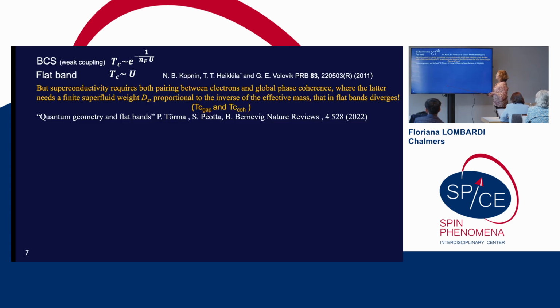However, flat bands have gotten so much attention because essentially if you have BCS, the TC is exponentially dependent on the product between density of states and interaction. Instead, in a flat band system, you can get that the TC becomes linear with interaction. So you could boost, in principle, superconductivity by using strong interaction and flat band. But superconductivity, as we heard the day before yesterday, doesn't require only pairing, but it requires also global coherence. And this is given by the superfluid weight.